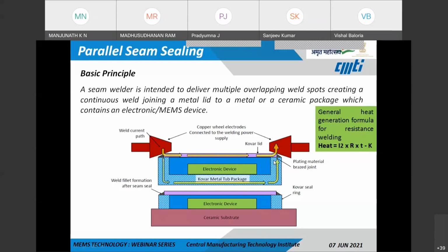While the other part of the device will be at a much lower temperature. Because of these high temperatures, they tend to volatilize the contaminants. So the weld will be a contaminant-free weld. Here there is also an application of pressure by the electrodes to hold the lid and case, which often accommodates a fair degree of non-flatness.